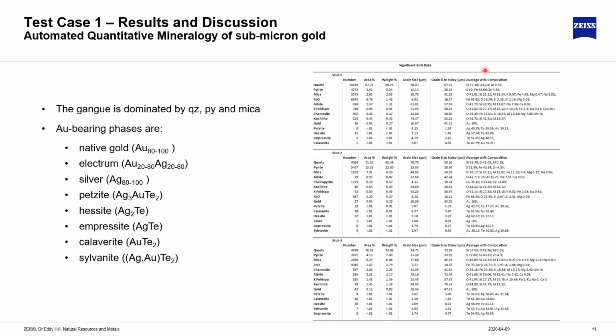We also immediately provide an average weight percent composition for each phase. And this table is presented immediately at the end of the analysis. There's no post-processing required. As a quick guide through, the gangue is dominated by quartz, pyrite, and mica. And the gold-bearing phases are native gold, electrum. There's some silver. There's a petzite, that's a silver gold telluride, hessite, that's a silver telluride, some empressite, again, silver telluride. And then we have calaverite and sylvanite as gold tellurides.